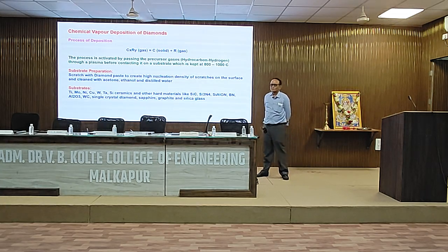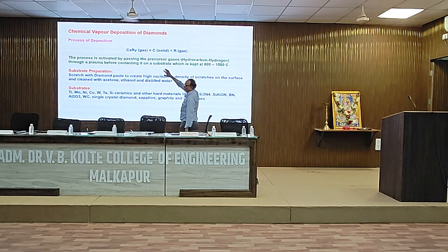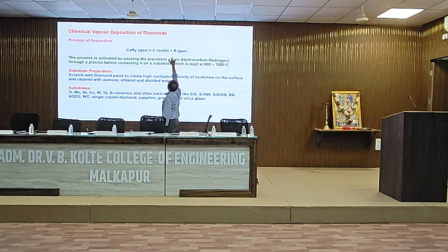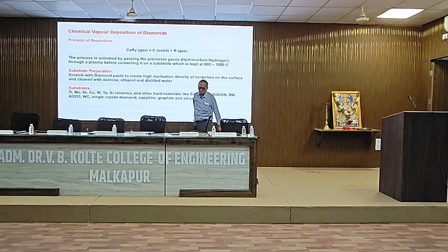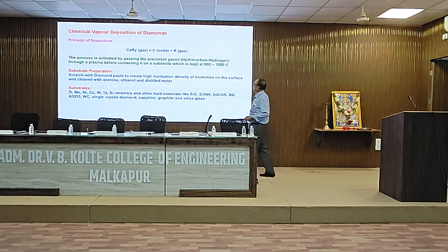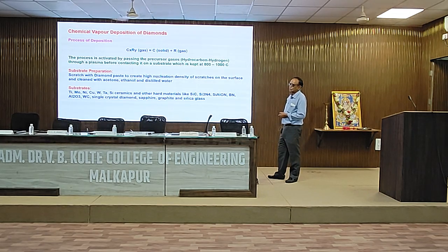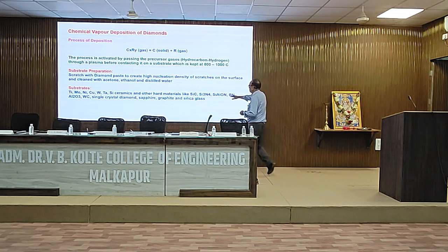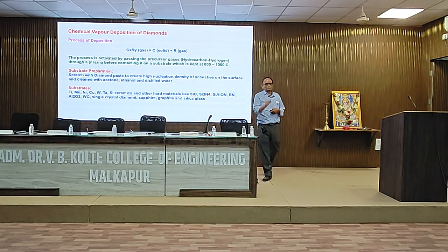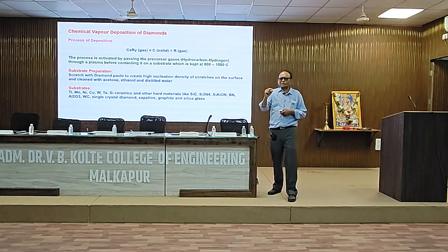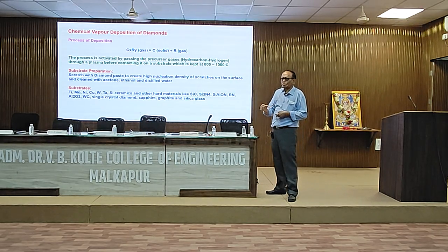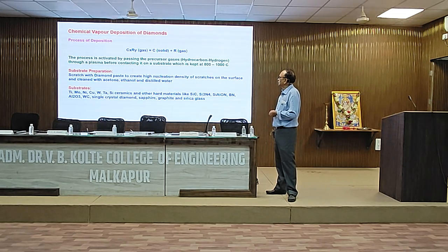Basic philosophy is, you have the methane gas, and this methane gas is decomposed in the plasma as carbon containing radicals and other decomposition products. And this process is activated by various hydrocarbon hydrogen plasma before contacting it on the substrate, that is kept at 800 degrees centigrade. Around 900 is the optimum temperature, and all kinds of substrates have been used for deposition of this coating. Nowadays, even millimeter thick or centimeter thick diamond coatings have been made. There are companies now all over the globe that are working on this area.